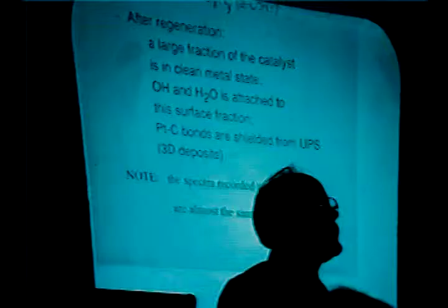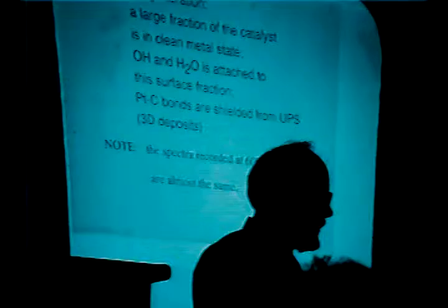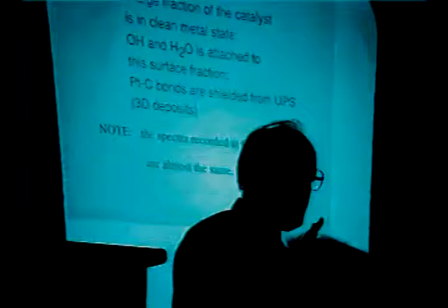Well, just to avoid the remark, okay, you treated the catalyst at high temperature, cooled down, and you froze all the species on the surface. To avoid this remark, I remind you that we recorded spectra at 600 Kelvin, even at 700 and 800 Kelvin, and the spectral features were essentially the same with some minor differences, so these surface species survive even high temperature. Now, you have another 4 minutes.